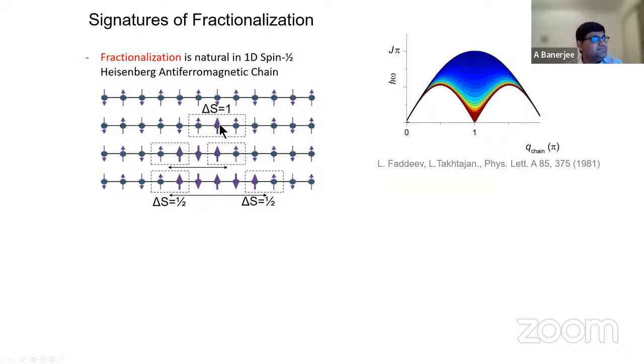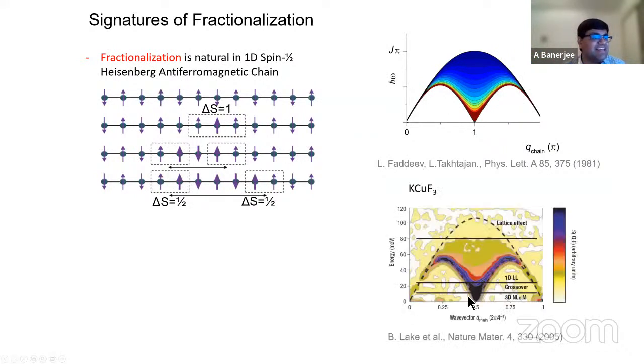Let's say you have this Heisenberg antiferromagnetic chain where you can create an S equal to 1 spinon, which fractionalizes into 2 spin-half solitons. You can calculate the spectrum directly using the Bethe ansatz. This is the momentum axis, and this is the energy axis. You see that you get this broad bunch of states, which is what you can predict. And that is exactly what has been measured in real materials which show this kind of phenomenon. You see this broad bunch of states. And it's not a random broad signature. It has a very specific energy momentum signature, and that's what you can really calculate and map.